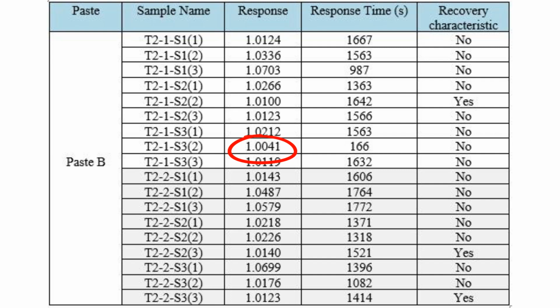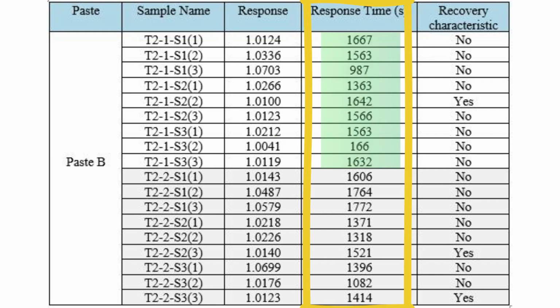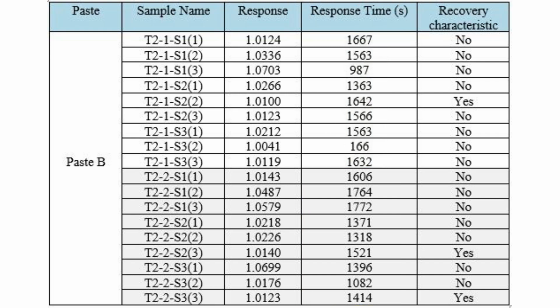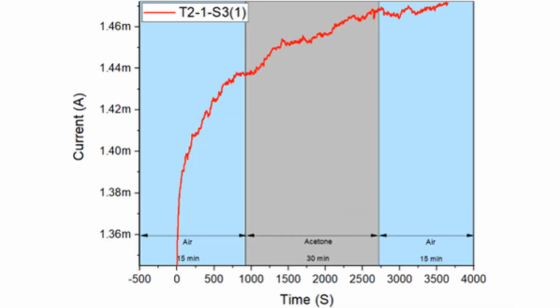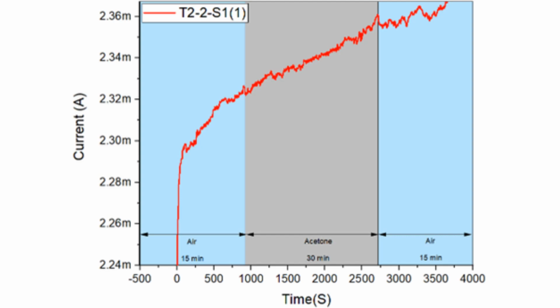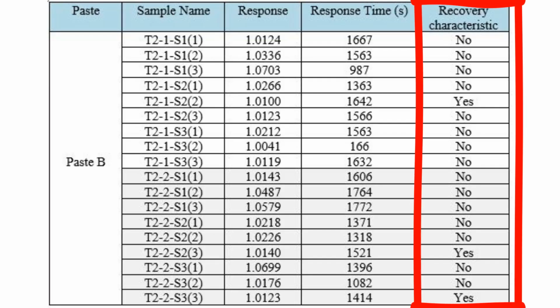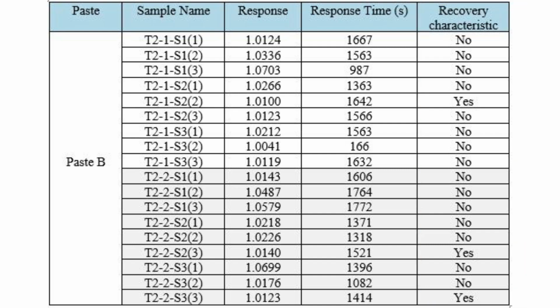As for the response time, the single layer shows a faster response time compared to the double layer, which is between 3 minutes to 29 minutes. The lowest response time produced by T21 sample 3 is 3 minutes, and the highest response time produced by T22 sample 1 is 29 minutes. Lastly, for recovery characteristic, most of the samples were unable to recover after the exposure to the acetone in 30 minutes.